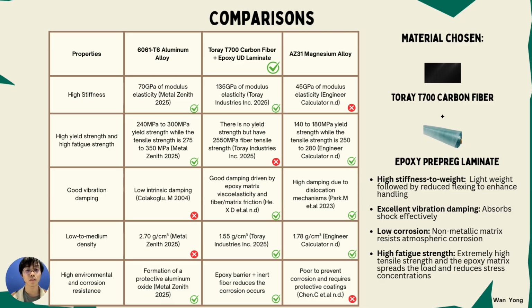Magnesium performs slightly better through dislocation motion, but the carbon fiber composite provides far superior damping. This is because the epoxy matrix is viscoelastic, meaning it absorbs the vibration energy, and friction between the fibers further increases the internal energy dissipation. As a result, the composite delivers smoother vibration behavior and reduces shock transmission.